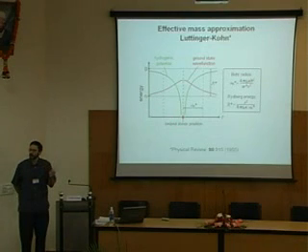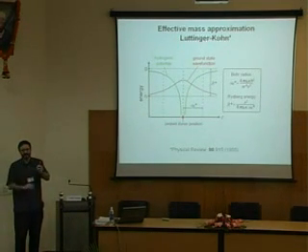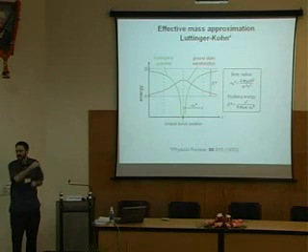It's given up 1 electron. You then ignore everything else about it, and you say, well, it has 1 more proton than an electron. Sure, it has a nucleus. It has lots of other electrons in there. We'll ignore all that and say, well, at some level, it's just like a single proton. You also ignore the lattice of all the other atoms around you, and you say, well, it's in a semiconductor. A semiconductor has a dielectric constant kappa. It has an effective mass for electrons. And if I just remember those 2 things, I can forget about the rest of the semiconductor as well. And so that's the picture.